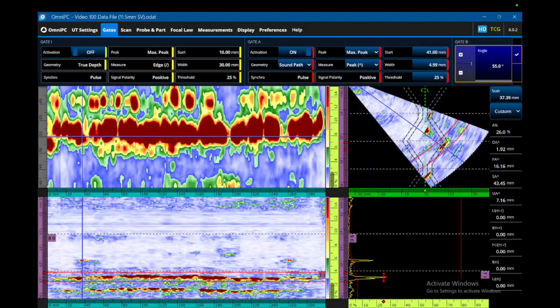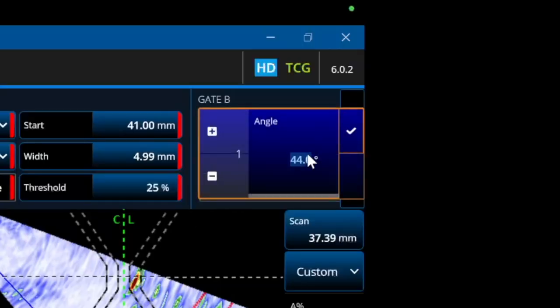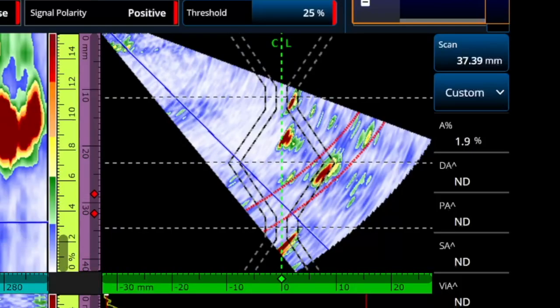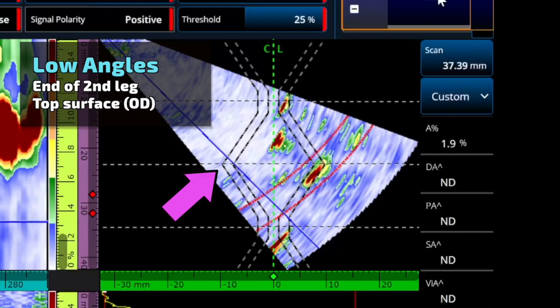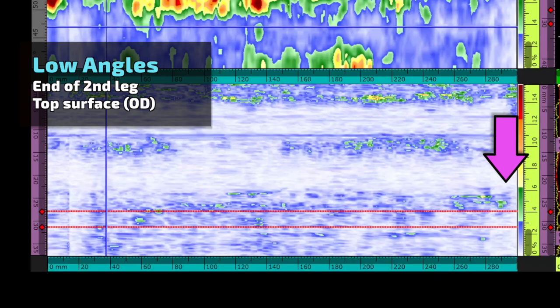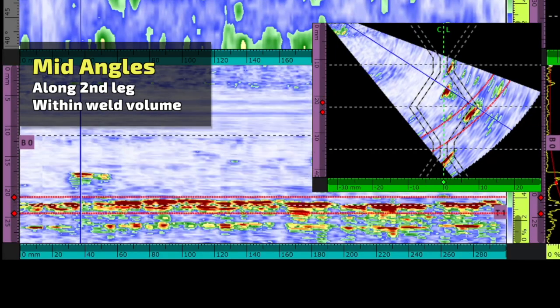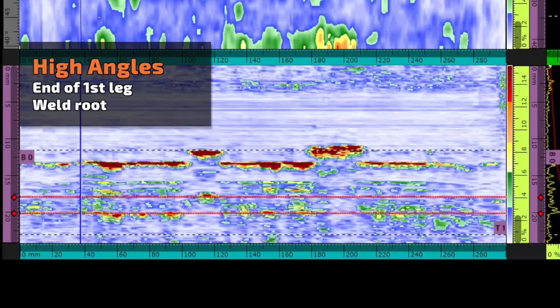Let's do this again. Slide the angle cursor back down to the bottom. I like to click up in the upper right-hand side and just use my mouse to scroll through and see if you can see anything. As we scroll from the bottom angles up, remember the low angles are going to be bouncing down here, hitting the upper cap on the near side of the probe. I don't see anything right there. As I slide this up, we're going to see one right there — that's that first one we wrote down at around 40 millimeters. And there's another one right there — those two are the near side root, already written down. Sliding back down a bit, you can see that other volumetric one at around 260 millimeters. Everything that showed up on the C-scan also shows up on the B-scan. Nothing new.